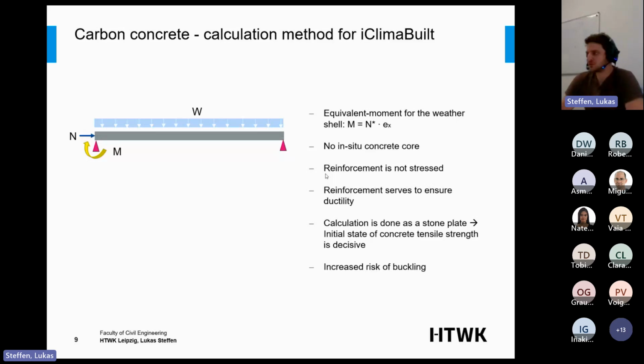So we don't really use it for the load bearing effect, but we use it to have ductility in the concrete, because if it gets cracked or brittle, you need the reinforcement, because otherwise it could happen that slabs of concrete fall out and harm people. So we need minimum reinforcement. The calculation I did for iClima is simply like a stone plate. So the main factor for the stability is the tensile strength of the concrete.